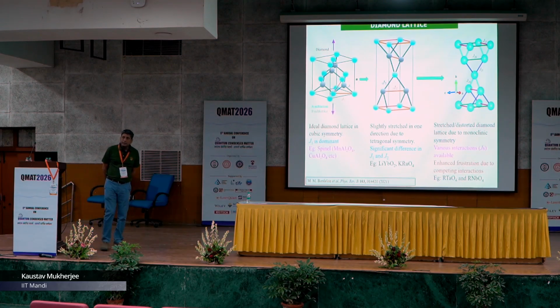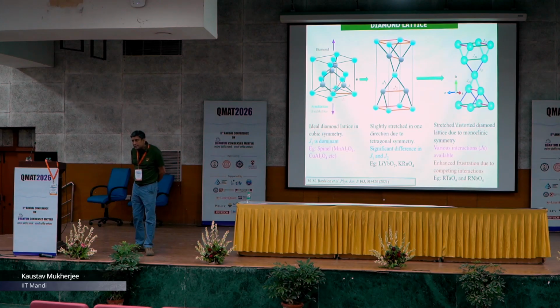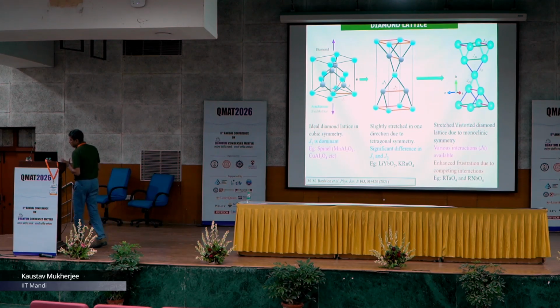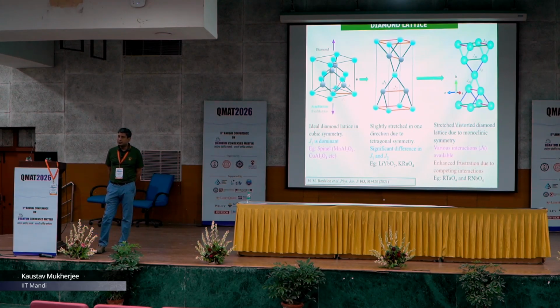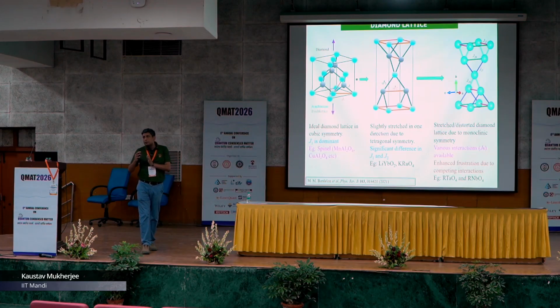Now, in my title I have mentioned the term stretched diamond lattice. So let's elaborate a bit on what I mean by this term. For that purpose we have to start with the diamond lattice. An ideal diamond lattice has a cubic symmetry, and when there is a cubic symmetry the nearest neighbor interaction dominates, the chance of frustration is minimal, and we can have long range ordering. Now suppose the diamond lattice is distorted a bit and it becomes tetragonal. Then the next nearest neighbor interaction, due to the bond length, can be comparable with J1, and so J1 and J2 can compete.